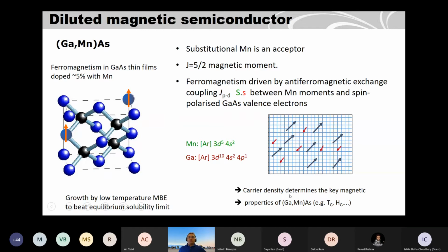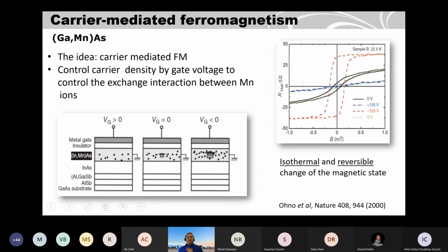And so these properties can be very well controlled because you can control the carrier density, because it's a semiconductor, and you can do this all by electric means. So for example, you have these magnetic moments and the electrons or holes that mediate the magnetism. So the advantage of semiconductor, as we discussed, is you can apply an electric field, the gate voltage, to tune the carrier density. So this is one example from a paper in 2000.